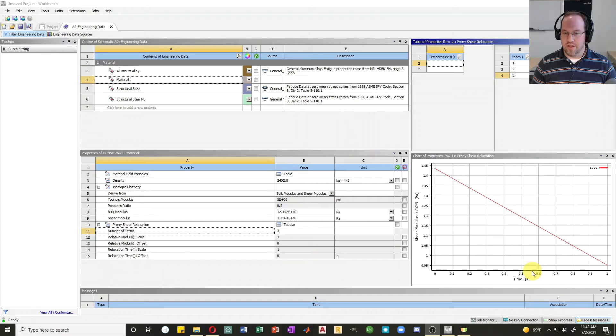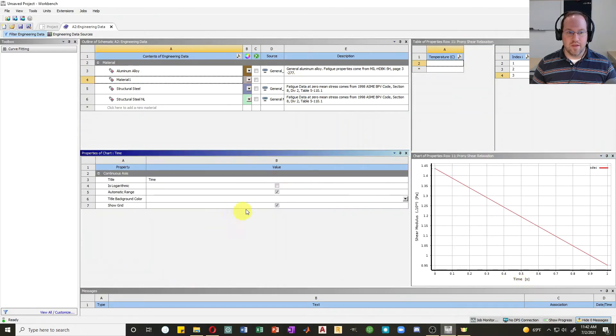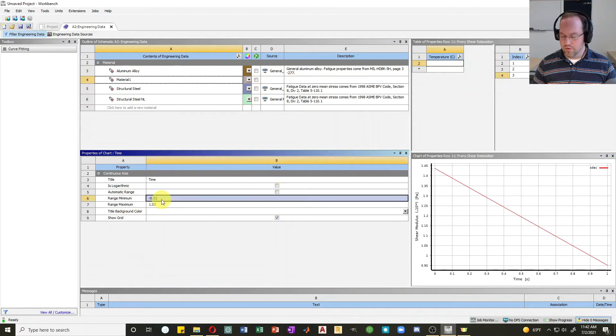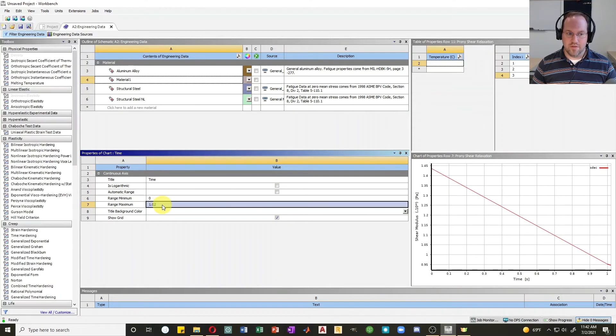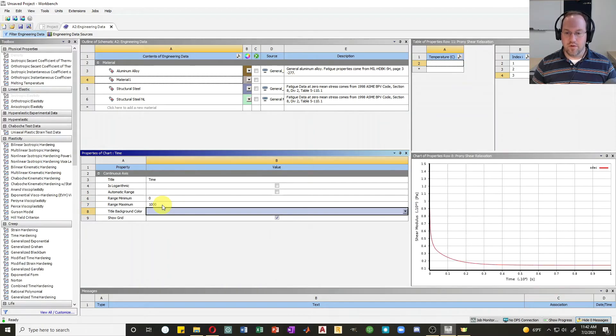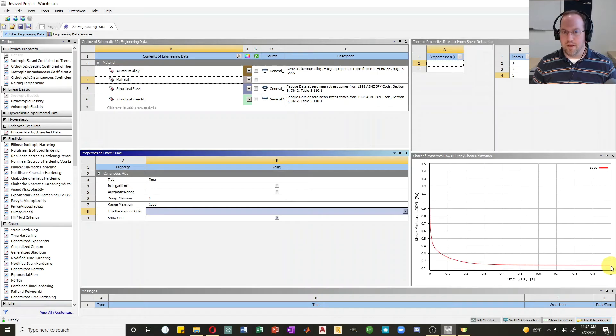There's a relaxation curve plot, but by default it only shows up to one second. Right-click on the x-axis, edit properties, and turn off the automatic range so I can set it to go from zero to 1000 seconds. Over 1000 seconds you can see it relaxes quickly and reaches an asymptotic value of 10% of the original modulus — because I've relaxed a total of 90% of my original modulus.